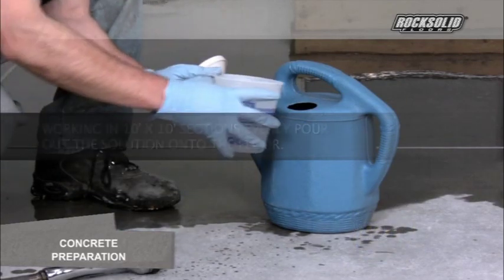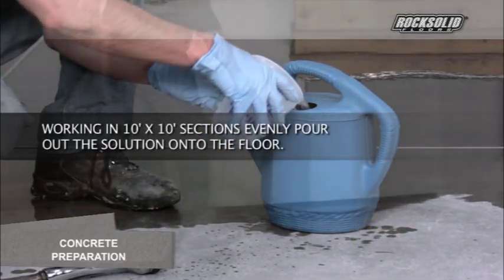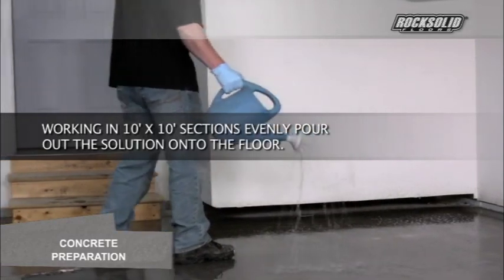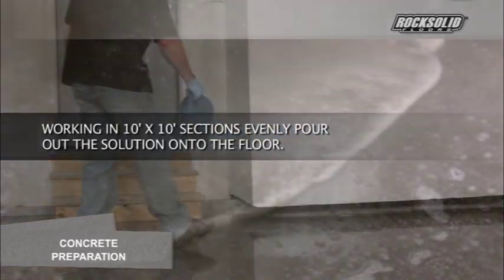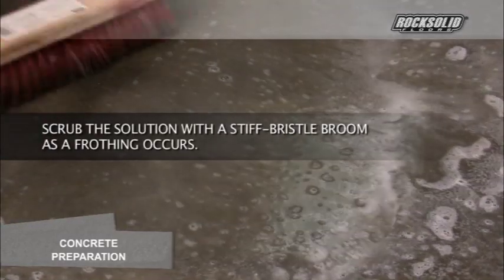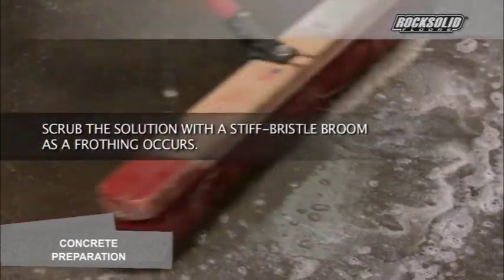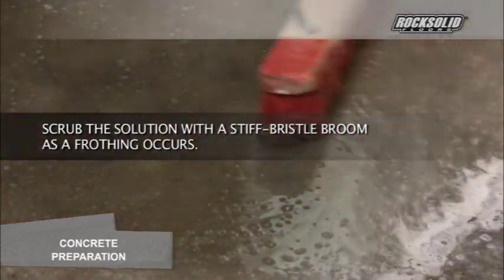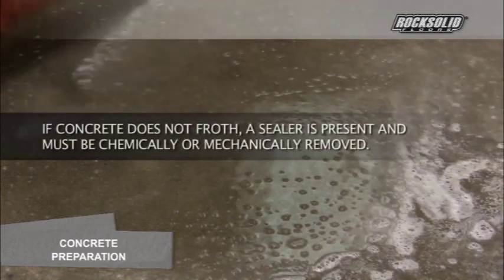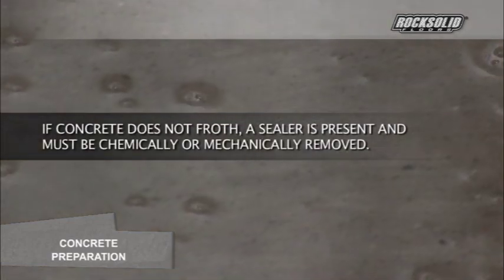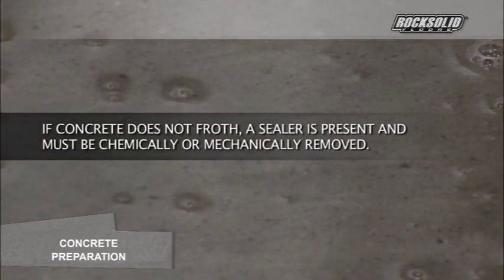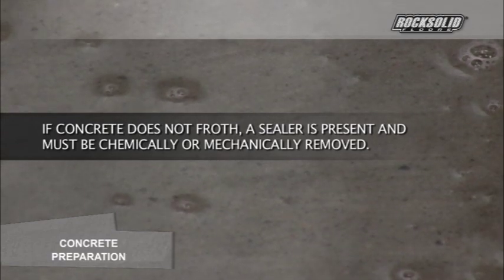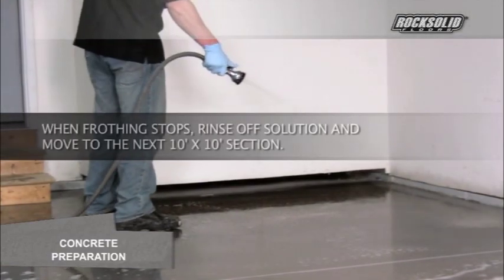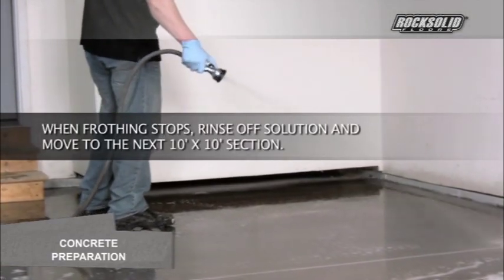Working in a 10 by 10 section of the floor, pour out the etching solution evenly on the floor. Scrub the solution around with a stiff bristle broom. Upon the initial application of the Safe Etch, a frothing should occur for a few seconds while being scrubbed. If the concrete does not froth, it means that there is a sealer on the floor and it must be chemically or mechanically removed. When the frothing stops, rinse the solution and move on to the next section.